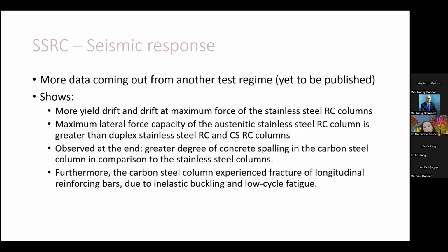And in summary, the outcomes of this research, and I think this is seen as a really good application for stainless steel reinforcement, again, owing to the ductility. There was more yield drift and drift at maximum force for the stainless steel reinforced concrete members compared with equivalent carbon steel. The maximum lateral force of the austenitic stainless steel reinforced concrete column was shown to be greater than for the duplex, which was quite interesting.